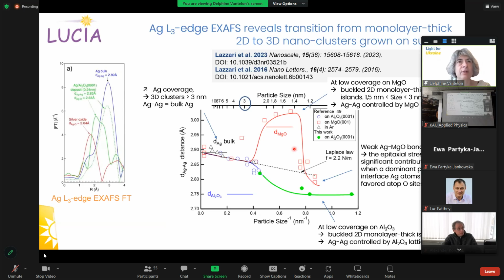And then I finish with surface science. These users could follow the arrangement of silver clusters on different surfaces, magnesium oxide and aluminium oxide, and in fact depositing different layers and amounts of silver on the surface. They could observe that below 3 nanometers of particle size, then the silver is forming monolayers. They followed it with the EXAFS of silver.